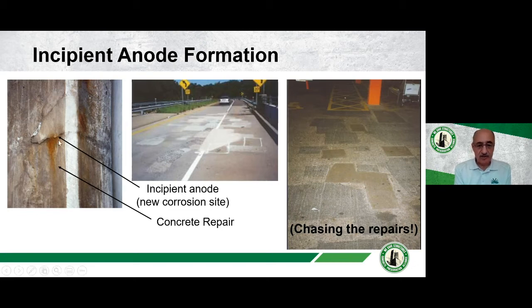And what you end up doing if you're not careful is chasing your repairs. You're repairing one area, it then forces corrosion to occur in adjacent areas, and then you go and repair those and so on, and you're just chasing your repairs. So we had to come up with a solution. We identified this problem as incipient anode formation.